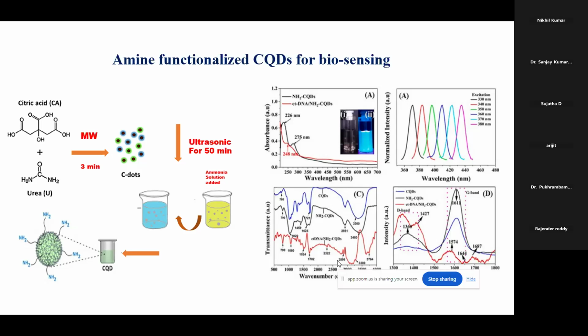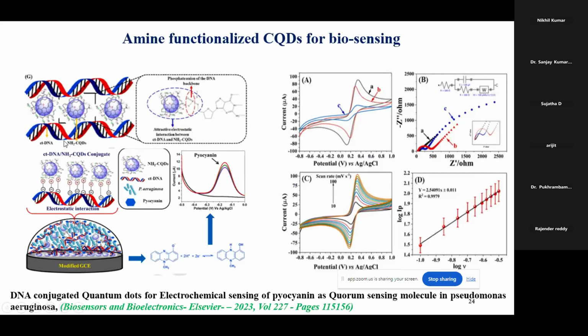For the electrochemical sensor we used this one, and the Raman spectra also show the D band and G band for carbon quantum dots. The DNA properties, adenine, thymine, cytosine, guanine, also showed. Then it got functionalized, and ctDNA is a structure and the functionalized CQD is a spherical structure. So it interacts and becomes an immobilized conjugate. It is coated on the GCE, then it gives the pyocyanin response. So we optimized this one and got results with the electrochemical sensing. This one also got published.